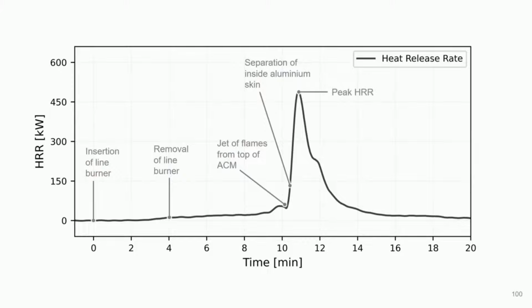It then increases to a peak heat release rate value. The polyethylene from the Reynobond PE gradually burns away over the course of a few minutes, and the foil-faced Kingspan Cooltherm K15 continues to smolder and flame, in this case until the experiment is terminated after 20 minutes. Again, a trigger warning is warranted here. This video I personally find particularly shocking.